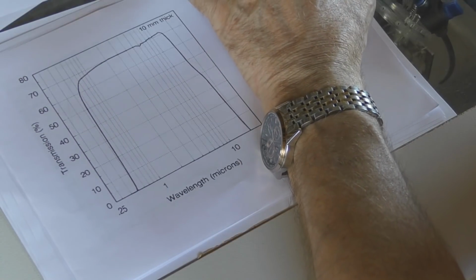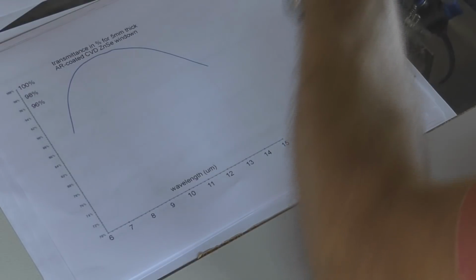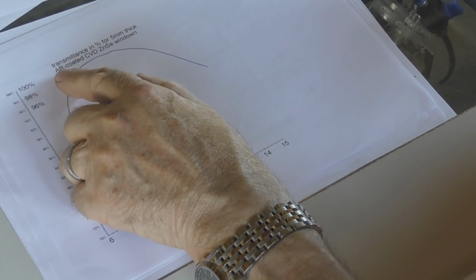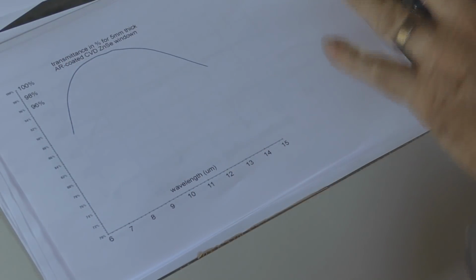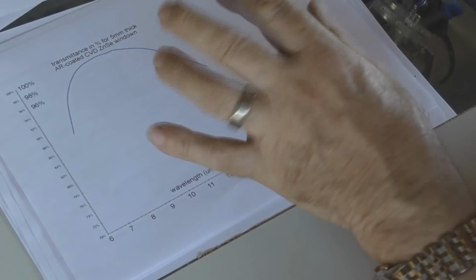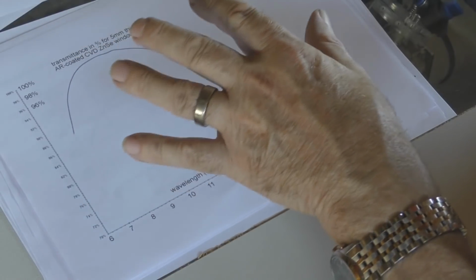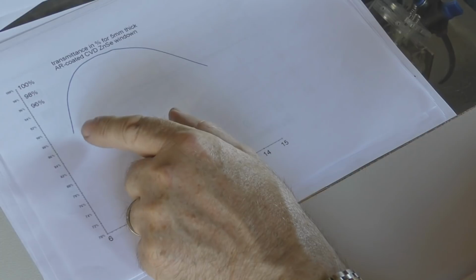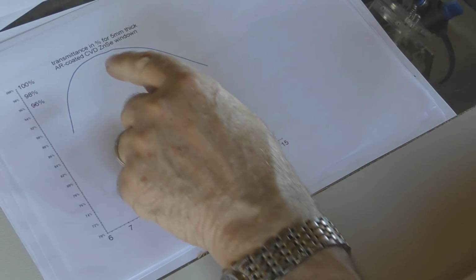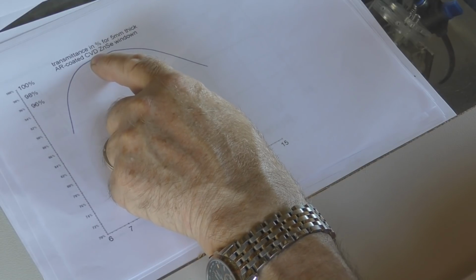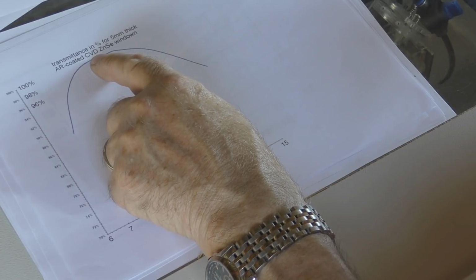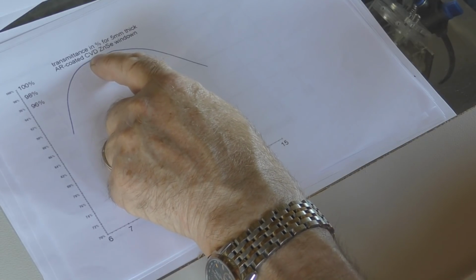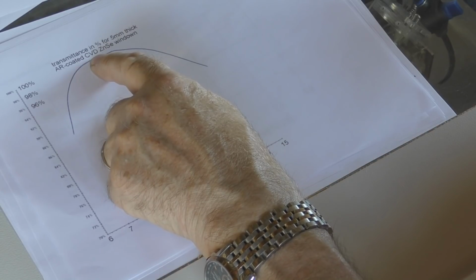Because what they can do with special coatings, special thicknesses, and special processes, they can add a coating, an anti-reflective coating, to the material. So when you look at your zinc selenide lens and you'll see that it's got a slightly strange greeny hue, that's the coating that's on the material. And it's an anti-reflective coating that actually promotes that 70% transmission up to 98-99% efficiency. So you can expect a zinc selenide lens, a good quality zinc selenide lens with the right sort of coating on it, to be up in the 99% efficient transmission range.